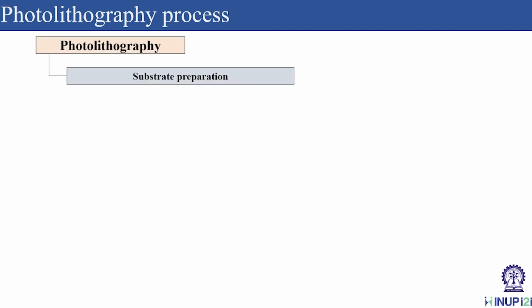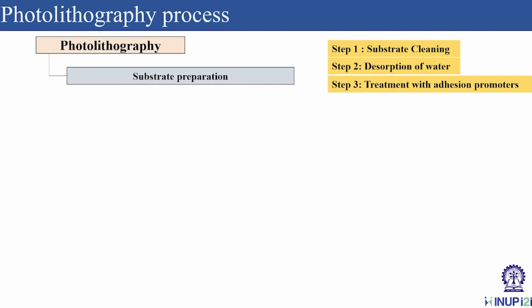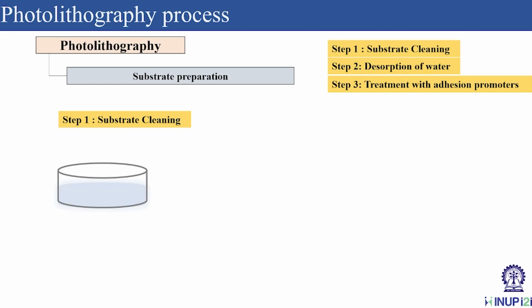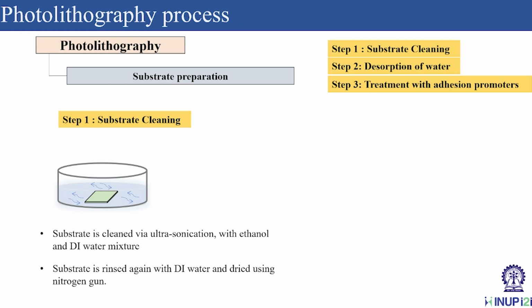The first step is substrate preparation, which consists of three steps: substrate cleaning, desorption of water and treatment with adhesion promoters. Before coating the substrate with the photoresist material, it needs to be cleaned thoroughly to remove any dust particles or organic contaminants present over the substrate. To clean the substrate, we mix ethanol and DI water, place the substrate in it and ultrasonicate it for a few minutes. Then it is rinsed off with DI water and dried using a nitrogen gun.